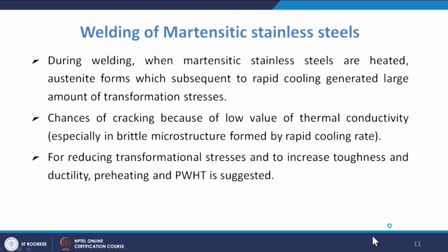So coming to the final one, welding of martensitic stainless steel. During welding, when martensitic stainless steels are heated, austenite forms, and with subsequent rapid cooling generally a large amount of transformation stresses develop. Because martensite has a larger volume compared to the austenitic phase, a lot of transformation stresses will generate. The chance of cracking increases because of the low thermal conductivity, especially with brittle microstructure formation by rapid cooling rate. For reducing the transformational stresses and increasing the toughness and ductility, preheating and post-weld heat treatment are suggested for martensitic stainless steels. Okay, so let's see some problems.